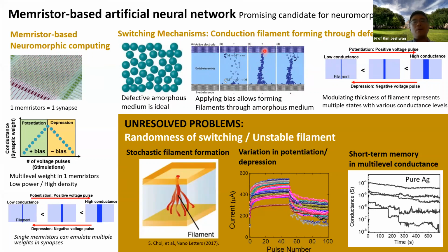If you completely send the metal from the top to the bottom, it makes a short, the on state. If you apply a negative bias, you can disconnect this filament, so you make the off state. Then how can you make this kind of analog potentiation and depression behavior? It's very simple. You apply the bias once with a very short pulse, and you make a filament. If you do it again, your filament becomes thicker by adding more positive ions. If you apply more, your filament gets thicker by receiving more ions. That is how you make the analog state, like a human brain, a human synapse. By applying a negative bias pulse, you can reduce the thickness of this filament, reduce the conductance, and change the weight in the artificial synapse, which is a memristor.